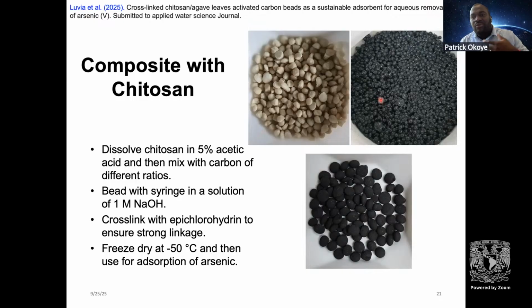We then cross-link this material because the challenge is that after this, it is only physically combined. The cross-linking stabilizes it against chemicals. For instance, if you are studying the effect of pH under acidic conditions and you do not cross-link this material, it will thoroughly dissolve. After cross-linking, we freeze dry to obtain these pellets that you see.